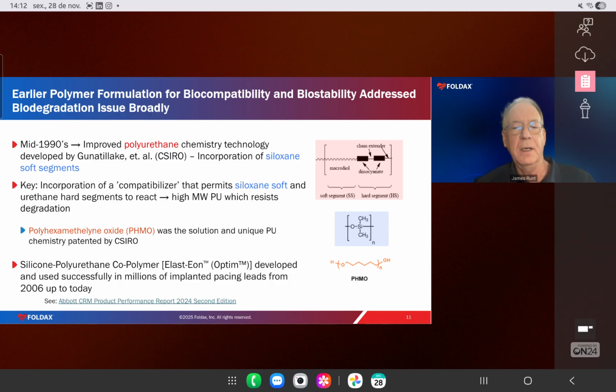And the key, the magic dust, was to use a compatibilizer, a chemical compatibilizer that permits the stable connectivity of siloxane soft and urethane hard segments, right? So the siloxane chemistry is shown in the blue box. And the compatibilizer is a simple polyether, which has a pretty long hydrocarbon segment in there. So that ends up at certain compositions.